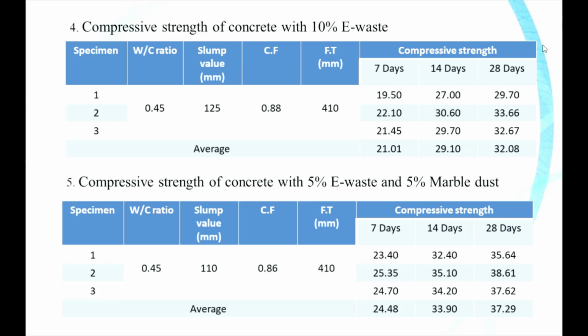So moving towards the next table, that is 5% addition of e-waste with 5% addition of marble dust as an additional material. In this, we have taken the water cement ratio 0.45, and the slump value is 110 mm, compaction factor value is 0.86, flow table value is 410 mm. So average of strength at 7 days is 24.48 megapascal. At 14 days 33.90 megapascal. At 28 days there is a strength of 37.29 megapascal.